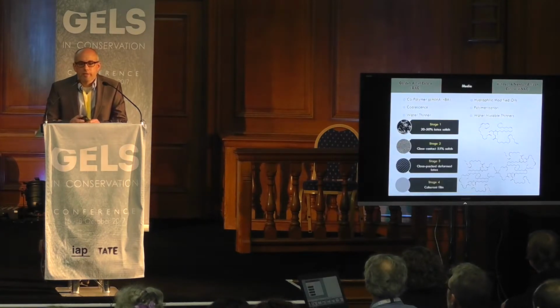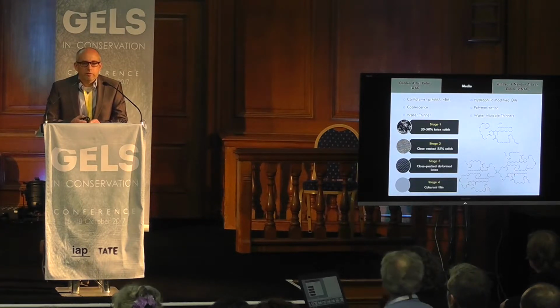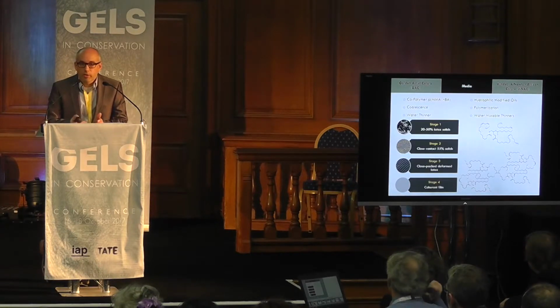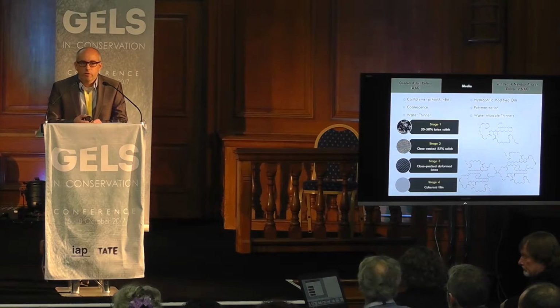So in considering the two different paint media, we know that emulsion polymerization paints, these acrylic polymers, coalesce. So the mechanism of film formation is coalescence. Particles of acrylic emulsion are suspended in an emulsion by surfactant. The particles grow closer together. They begin to form a film. And then at some point, the surfactant is really no longer needed. The surfactant is left in the bulk of the paint film. It can move to the surface of the paint film, but it becomes part of that artwork. It becomes part of that piece, even though it serves no function after it's coalesced.